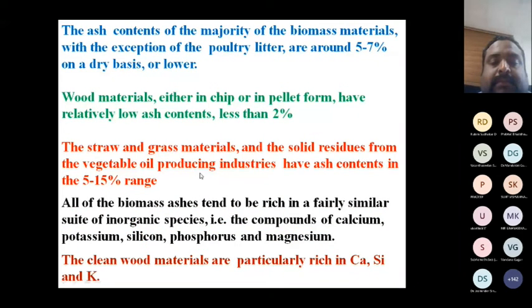The ash content of the majority of biomass materials, with the exception of poultry litter, is around 5 to 7% on dry basis. Wood materials have less than 2%, as you see with sawdust. Straw and grass materials and solid residues from vegetable oil producing industries have ash content of 5 to 15%. We have seen that rice straw and wheat straw are around 14%. All biomass ashes tend to be rich in a fairly similar suite of inorganic species. Compounds of calcium, potassium, silicon, phosphorus, and magnesium will be there. Clean wood is rich in calcium, silicon, and potassium.